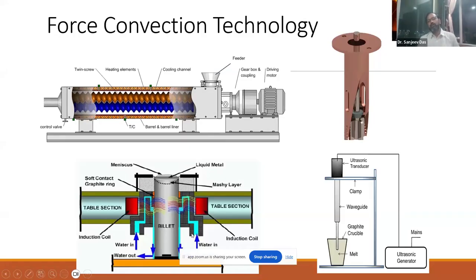By electromagnetic forces, by Lorentz forces, you can stir the liquid metal. So this is a very good one, because here there is no contact between the electromagnet and the liquid metal. The electromagnet can be outside the mold, right? And then the electromagnetic field will penetrate in and stir the liquid metal.